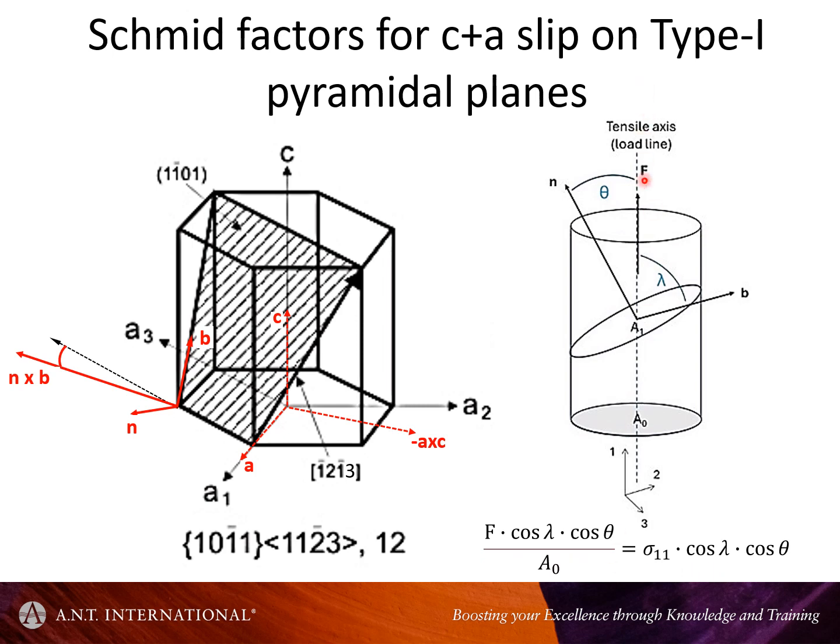If we had a simple tensile stress, the actual shear stress is in the direction of the Burgers vector, the direction in which the material can shear. It can't shear in all directions, it can only shear in specific directions, depending on which Burgers vector is possible on that plane. You resolve this tensile load onto the plane, which is parallel with the slip plane and parallel with the Burgers vector, the allowed direction for slip.